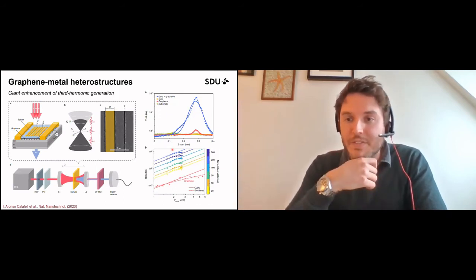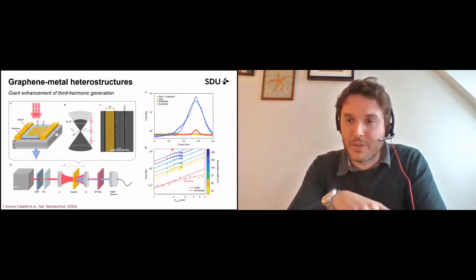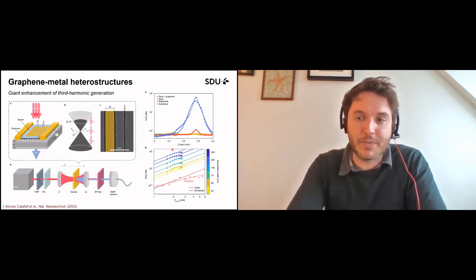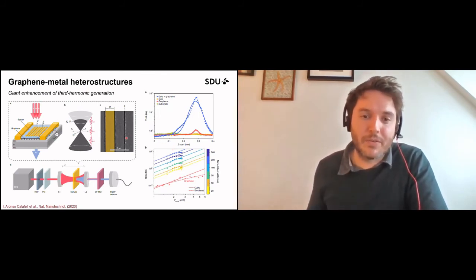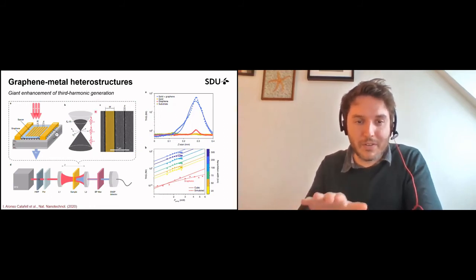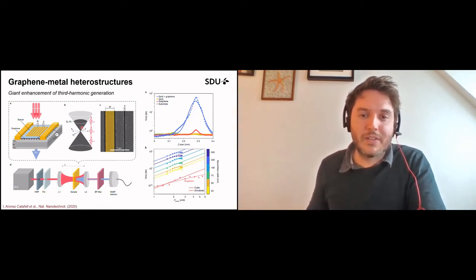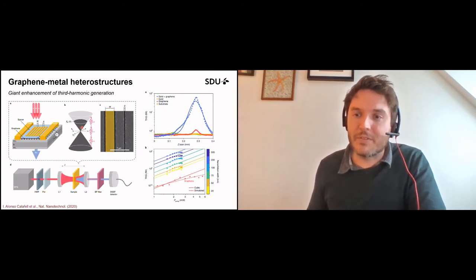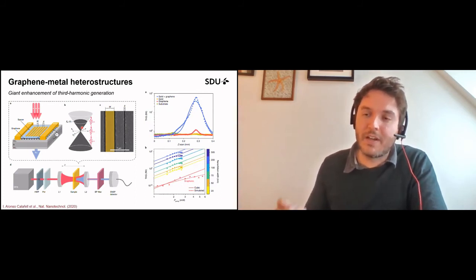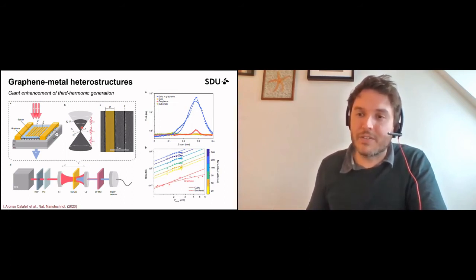And finally, just a few months ago, the researchers in Vienna I mentioned, who are doing experimental research, were able to show that combining graphene with a metal nanoribbon can dramatically enhance its nonlinear optical properties. In particular, for third harmonic generation, they were able to observe a substantial effect. And they were also able to show how you can tune the nonlinearity through electrostatic gating of the graphene. So again, you can actively tune the nonlinear response.